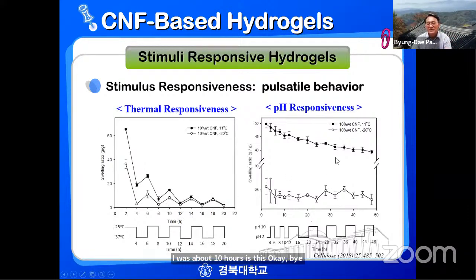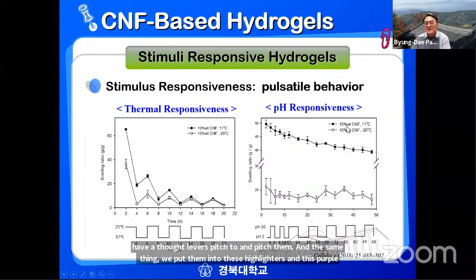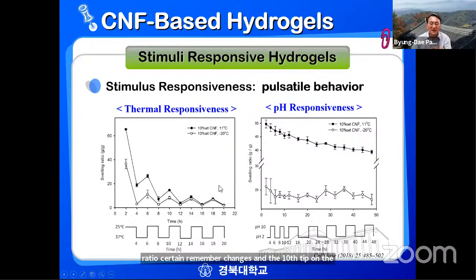But pH response is not good. We have two levels, pH 2 and pH 10. And the same thing, we put them into these buffer solutions, and then check the swelling ratio. Swelling ratio not much changes, and the different polymerization temperature. That means the hydrogel is very responsive to temperature. I would say less responsive to the pH.